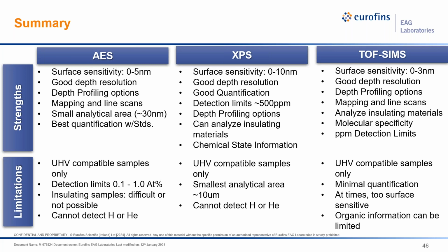They all require that samples be UHV compatible, although we do have cold stage options. So if we're looking at something, say like an intraocular lens that is a wetted surface, we can freeze these, maintain the surface chemistry in vacuum conditions in the frozen state.